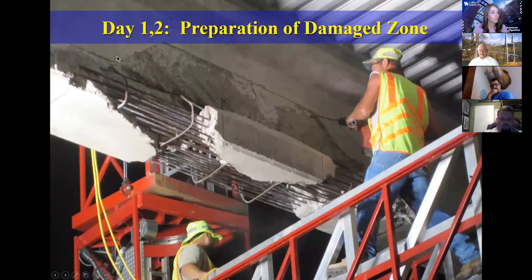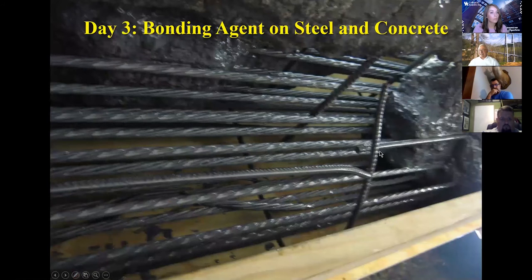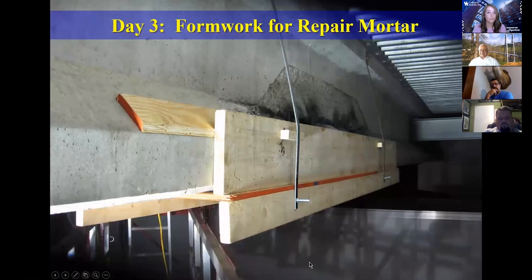If you've repaired concrete, you follow geometric shapes to be able to place the new concrete in there. You sandblast the strands in this case and put coating on them. You can see this strand comes this way and it's bent that way. And this one was actually cut. There were about, I believe, 3 strands that were severely damaged on this. So we cannot really come back and put new strands in there with ease. So we're going to reinforce it from the outside.